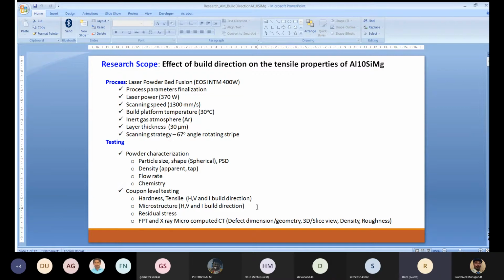The reason is it helps you minimize the anisotropy. You are not making the heat flow in the same direction in each layer. Thereby, you are disturbing the grain orientation in each layer, so that you get more randomized grains or very little texture in the component.